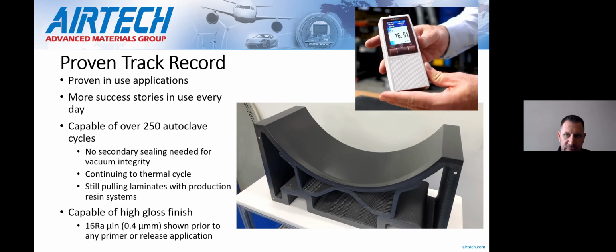So, even in this tool here, we're seeing about a 16 RA micro-inch finish with just basic post-processing. So printing, milling, and then some basic hand finishing and a tooling sealer applied. And so we're seeing these vacuum integrity benefits and surface finish benefits of the 16 RA, for example, even before a primer or anything else goes on the tool. I'd say typically most of our customers are looking for something around a 32 to 63 RA micro-inch, and that's easily achievable. And again, vacuum integral and as a fully durable finish.